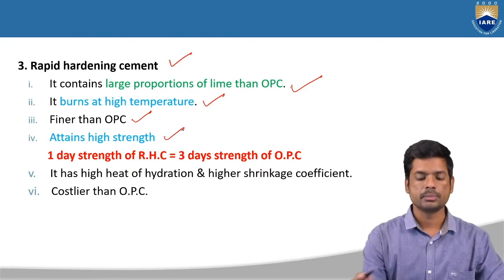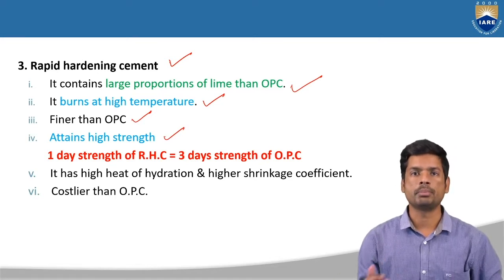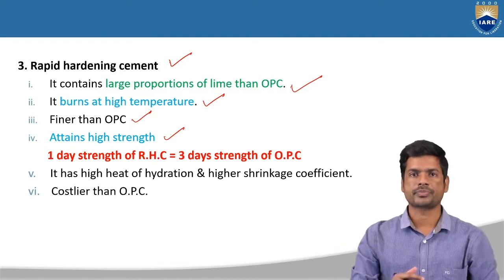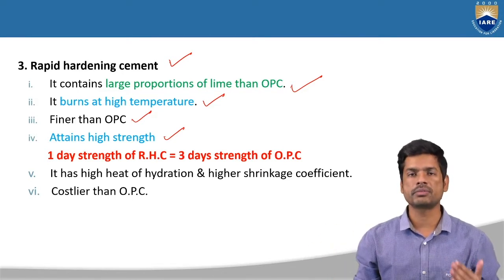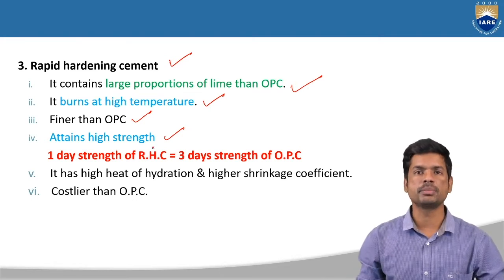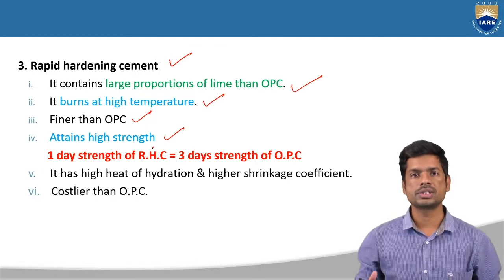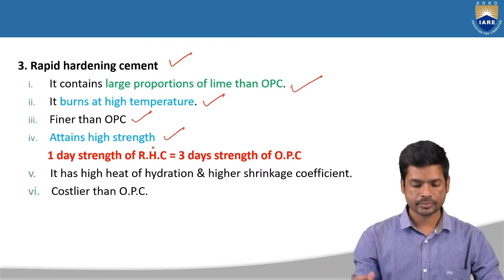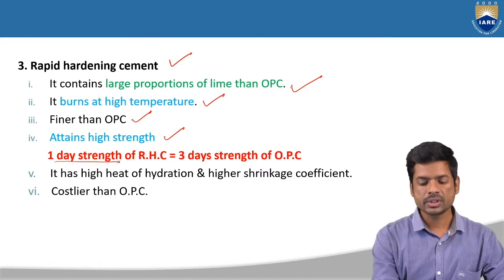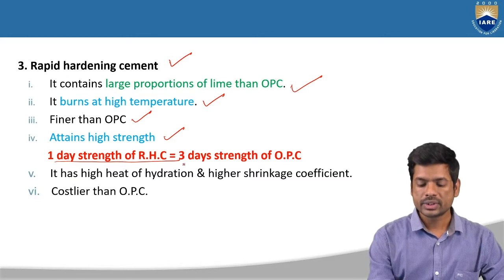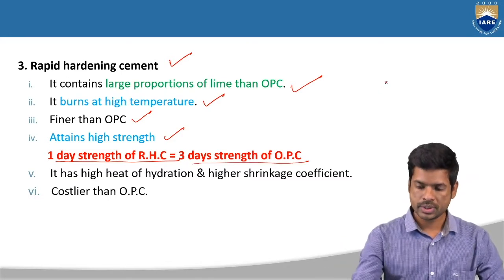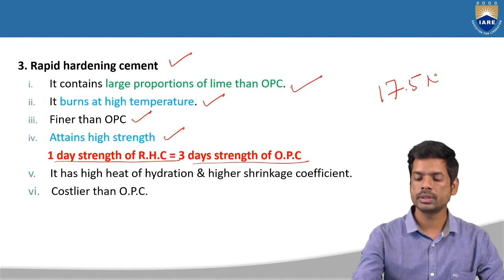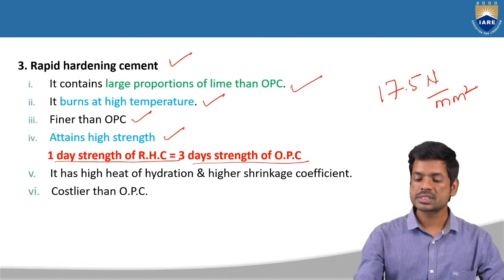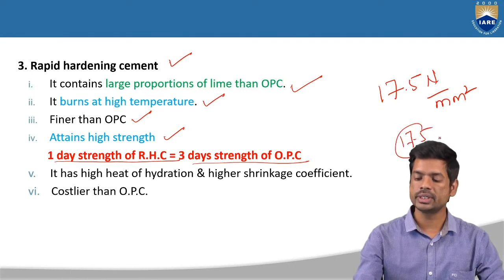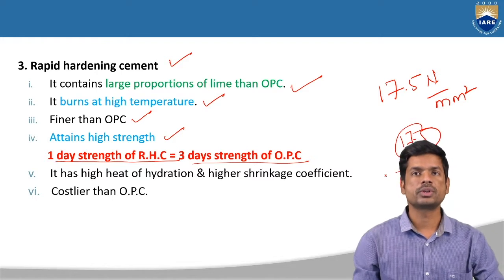Next, it attains high strength, because the hardening of this cement is very rapid. Within a short time it is going to gain a high amount of strength when you compare with the ordinary Portland cement. Let me tell you the strength of the hardening cement. The 1 day strength of the RHC, that means rapid hardening cement, is equal to the 3 day strength of OPC. If you take OPC strength after 3 days or after 7 days, the strength will be around 17.5 Newton per mm square. But here that 17.5 strength will be achieved in 1 day itself. So that is the benefit of this rapid hardening cement.